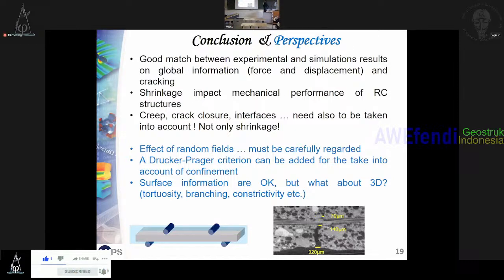I would also like to emphasize that in some cases it's important to predict the shrinkage, because as I said before, it can be positive or negative. Here it was negative, so in order to predict more correctly, it's important to take shrinkage into account. And it's not only shrinkage, you also have to take into account creep. So it's a little bit more complicated. Crack closure, if you have evolution of force applied, but also the interface. So it's not so easy to predict the behavior of concrete structures when you have evolution of temperature and relative humidity.